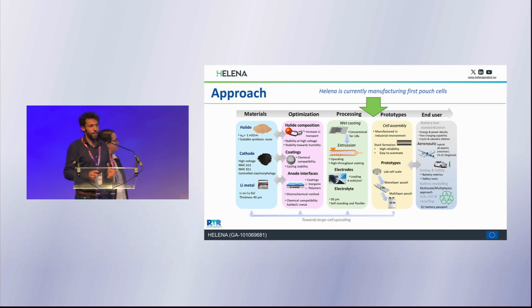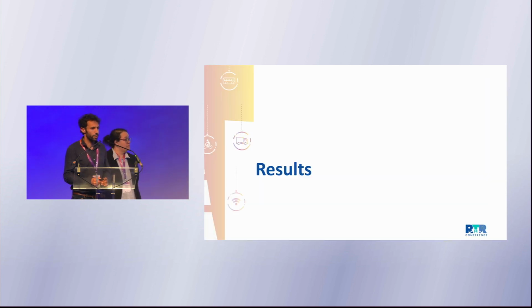We are aiming for very thin layers of halide electrolyte to reach the energy density that we are targeting. And finally, on the later phase, we are making these prototypes from a lab cell scale to large pouch cells for final validation in the application with the specifications that are set by the end user. So in this whole phase, there is the transversal activity of the battery modeling, which serves as a guideline to help to make better materials and to build better solid-state batteries.